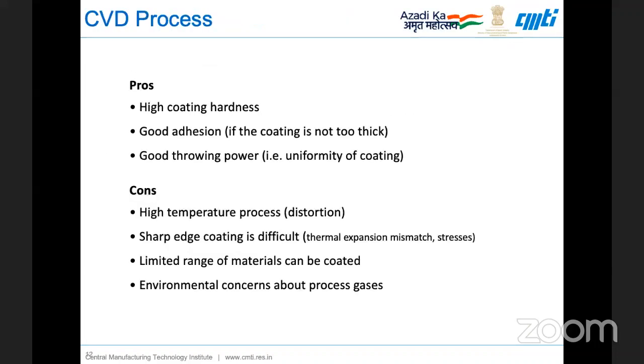So what are the pros and cons? The pros are basically high coating hardness, good adhesion, good throwing power, whereas the negatives of the process would be that it's typically a high temperature process, and you could end up with a certain amount of distortion. Sharp edge coating is slightly difficult because, let's say, if there's a burr in that region, thermal stresses are likely to develop and the peel off starts from that place. A limited range of materials can be coated, and of course, there are environmental concerns with respect to the release of process gases. So you have to put in a scrubber, though that is of course not for all gases. Let's say if you're using a silicon-based gas like silane, then you will have to put in a scrubber and burn it out and then release it to the atmosphere.